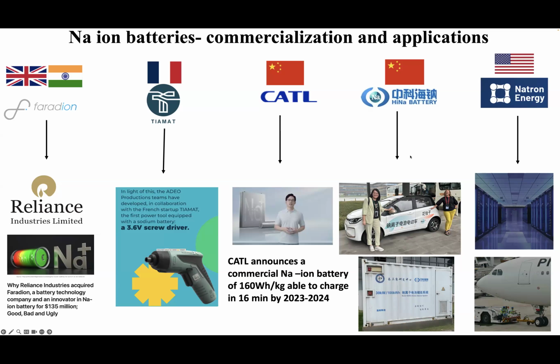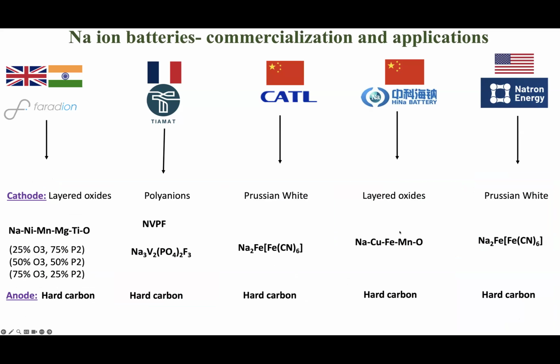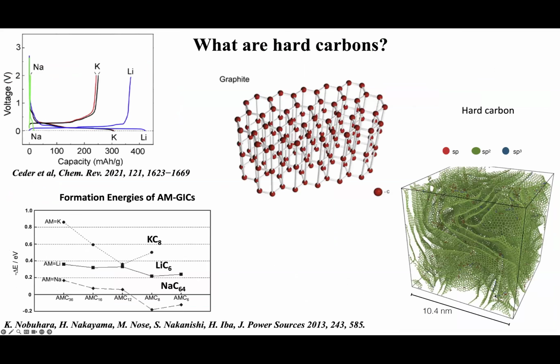And this is actually the closest I've seen myself personally, sodium-ion batteries being commercial, and there's Natron Energy in the US, which is using sodium-ion battery for data storage or pulling large things like aeroplanes around the airports. And they all have different chemistries in terms of cathodes, and you would see that they are all relying on these hard carbon anodes, which are quite difficult materials to study, and that's what we did.